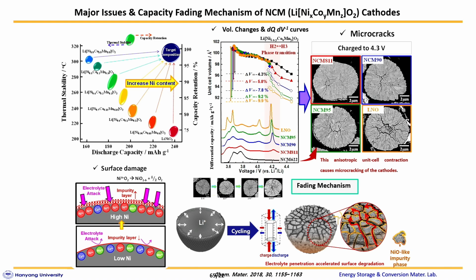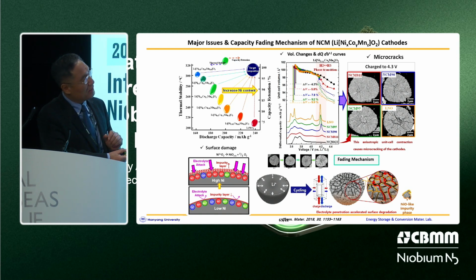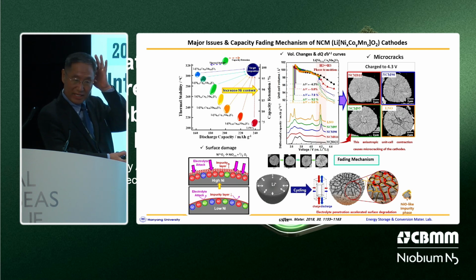As you can see here, this data was carried out by in-situ XRD. The unit cell volume monotonously decreased up to 4.1 volt, and then rapidly decreased above 4.2 volt, which corresponds to the H2-H3 phase transition. In addition, you can see the unit cell volume variation increases with increasing nickel content. For example, this value is 4.3% for NCM622 and almost 10% for pure LNO. And I believe that the anisotropic volume contraction causes the micro-cracking of the cathode.